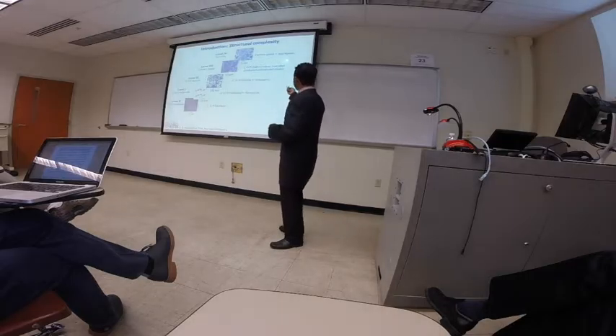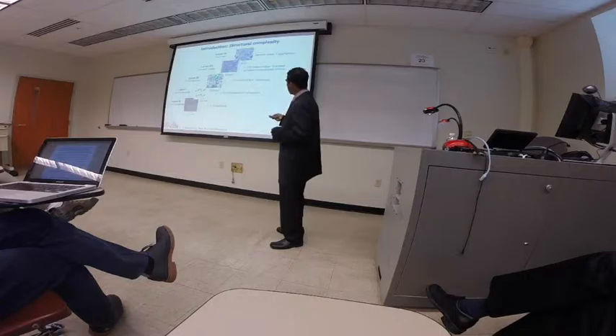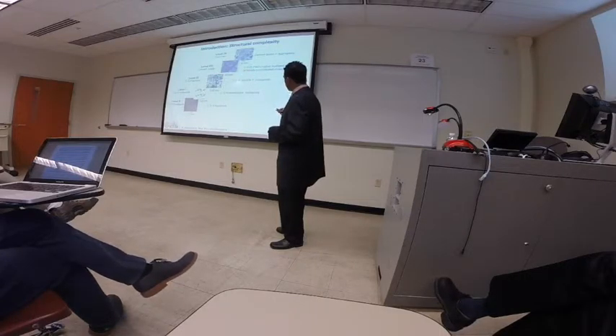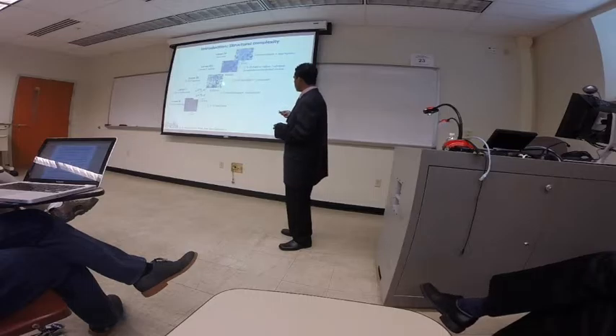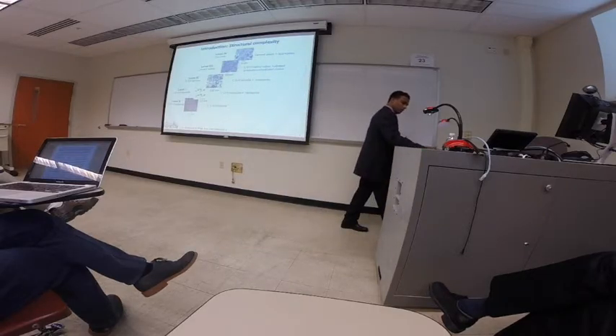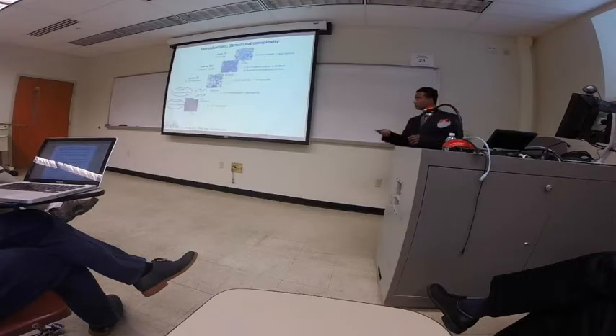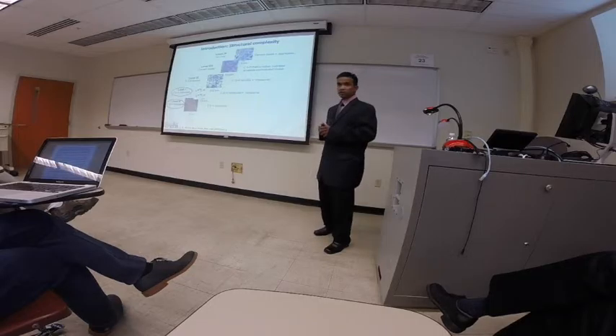This picture gives you the structural complexity of cement, starting from the cement paste that you find in the walls. At each length scale, you can see that the CSH matrix is made up of, as far as we can tell, different structural arrangements. It is a porous material inherently, and porosity has an inherent role to play in this. As far as simulation goes, we are basically focusing on these two levels at nanoscale to find an atomistic model for cement.